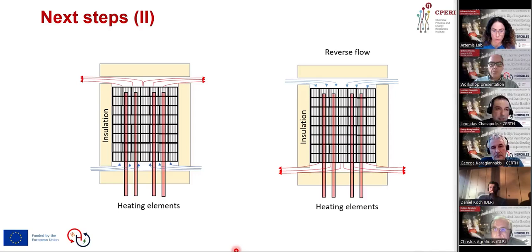Another important modification will be to adjust the reactor geometry, making it longer and allowing for a reversible gas flow. This will increase the contact time between the reactive gas and the storage material and help us achieve a more uniform thermal distribution. The reverse flow capability is especially important for reducing the colder regions and improving the overall reduction degree of the material.